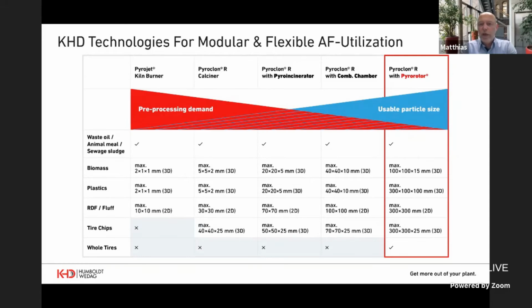This table shows you the range of combustion technologies that KHD is offering in order to fulfill these individual requirements. You can read this table from the left-hand side to the right-hand side with decreasing requirement of pre-processing, meaning that if you have a high-quality fluff, for example, you can use the Pyro Jet kiln burner or the regular calciner technology to utilize these. But if you have low pre-processed material, big size particles, high density particles, or biogenic particles like wood, which is dense, or you have moist materials which require longer retention times, you would use this Pyrorotor machine, which I will show you in closer detail in a second.